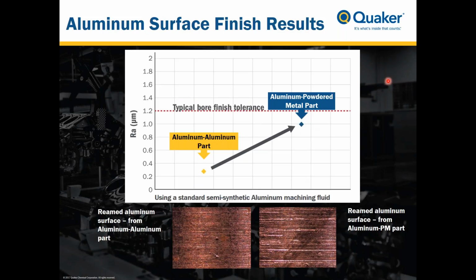Regarding the surface finish, again, looking at the aluminum part, when we measured the aluminum surface finish, we get a very smooth surface quality, surface texture, surface profile. The reamed hole Ra is under 0.3 microns, and this is a very good smooth surface. You can see a microphotograph of this surface below the graph. If you go to the aluminum surface that was produced in the bimetal part, you can see the noticeable degradation of the surface finish, both in the Ra, which measured up around 1.0 micron, and visually in the photograph of the reamed surface. Here you can see notable scratches in the surface and in general a tendency towards a rougher, abraded surface.